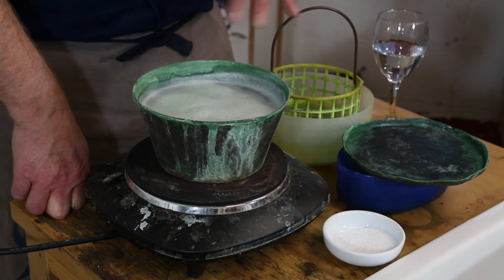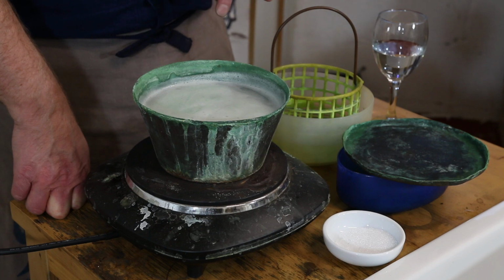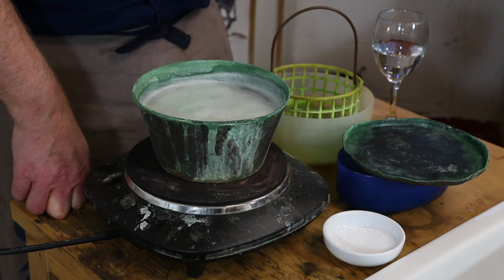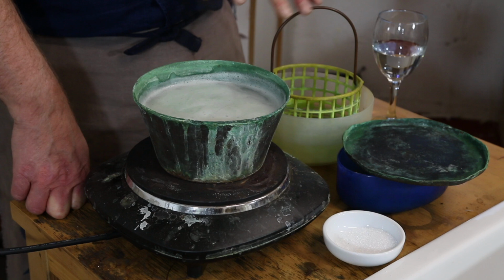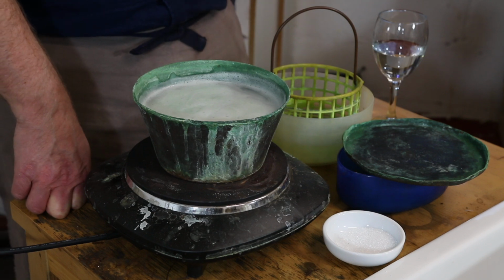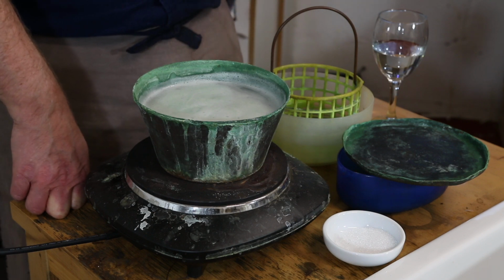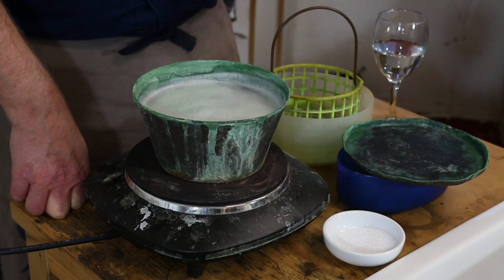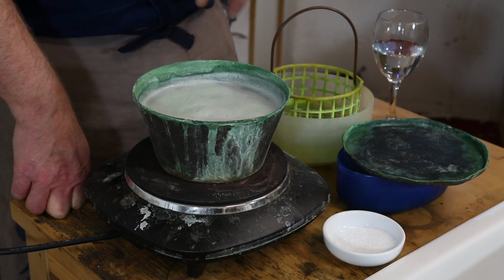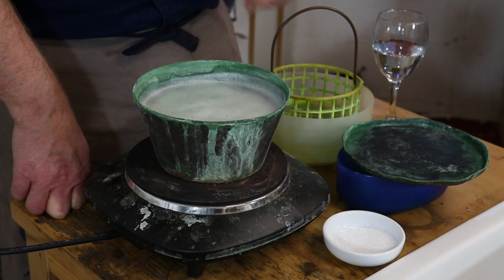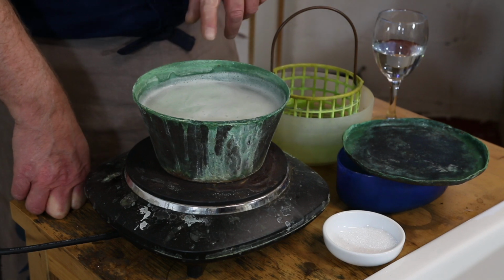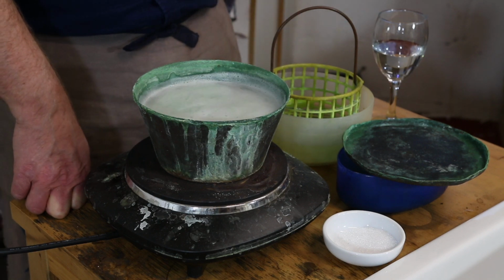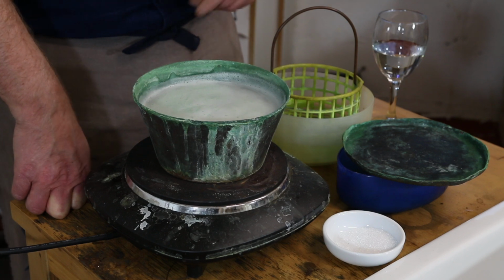Right, so the pot's been warming up for the last 10-15 minutes. It's quite close to boiling now. Chances are if I were to go away and do something, I'd come back to find this all boiled over. So it's really critical, as I say, at the first instance, when you bring it up to temp. I can see the surface is starting to shake. There's quite a lot of activity underneath the foam.